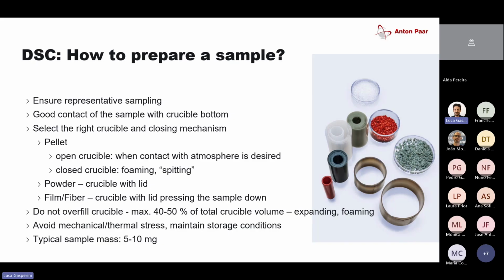Powder samples, yeah, we can also measure powders in the DSC. Then I would always go for a crucible with a lid, because of the manipulation and handling. If it's a very fine powder, like a very fluffy thing, then between the time that you actually take the mass in a balance and you need to move it around to the instrument, you might lose the material. And if your sample mass is not very accurate, then of course the quantification goes bust. Because if I'm telling the system I have 10 milligrams of sample, but on my way I've lost 2, then of course the quantification is no longer valid.